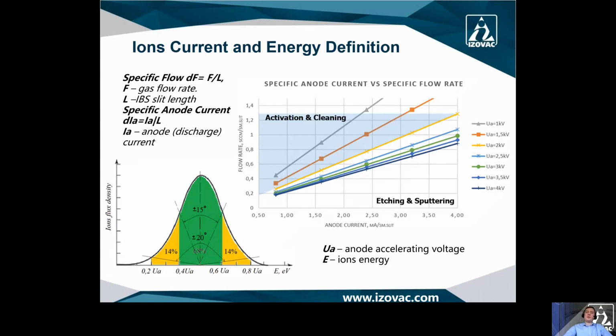Ion current and energy definition is quite an important issue during the solution design. There are 2 graphs to help you do it. One graph represents specific anode current dependence on specific flow rate. Another graph represents dependence of ion energy and ion flux density. When we're talking about mean energy, we're talking about peak energy, and more than 68% of all ions are in this region. And this inclined angle will be plus minus 15 degrees.